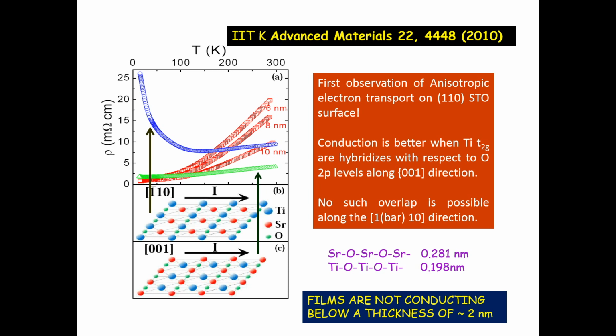And you have to be very careful to do this experiment, because if you do a 4-probe measurement, then all your current directions get mixed up. You have to cut the sample into a very thin slab along a particular direction, the other one in the other direction, and then measure.